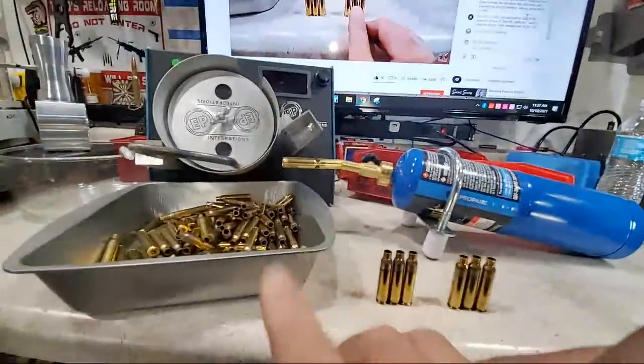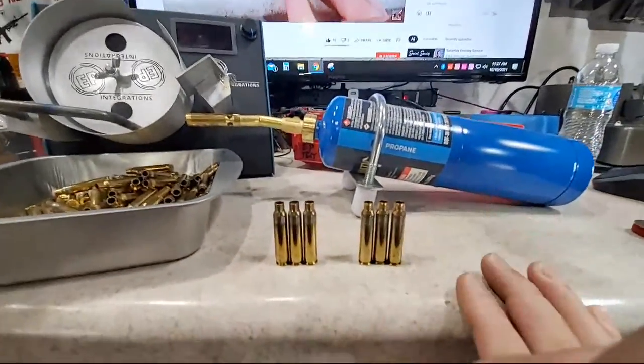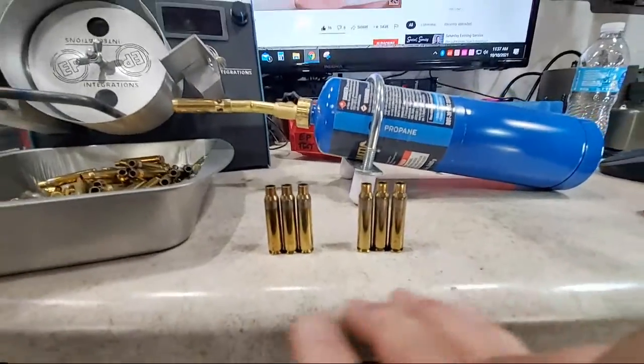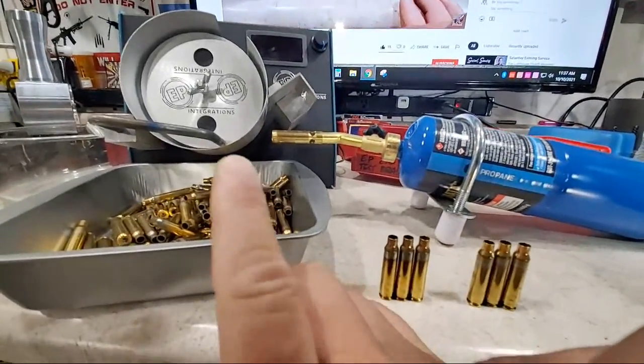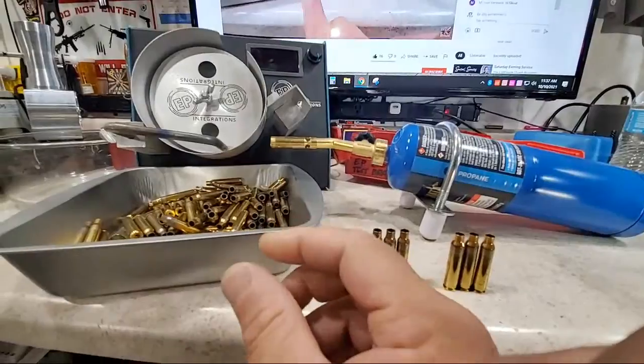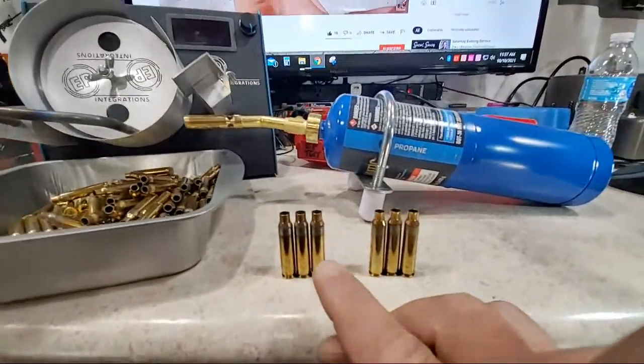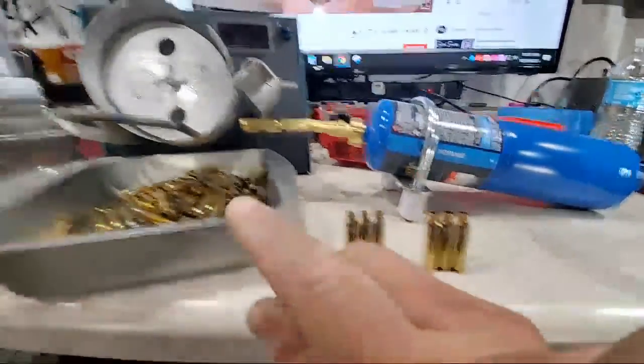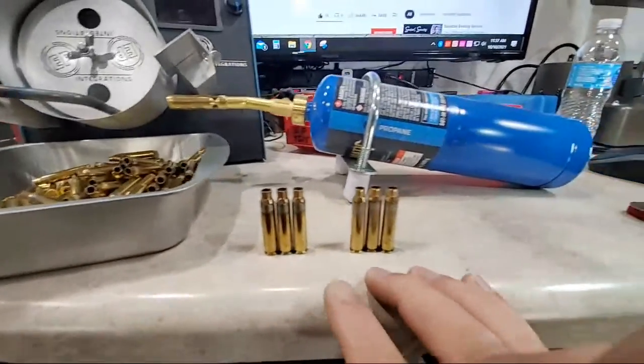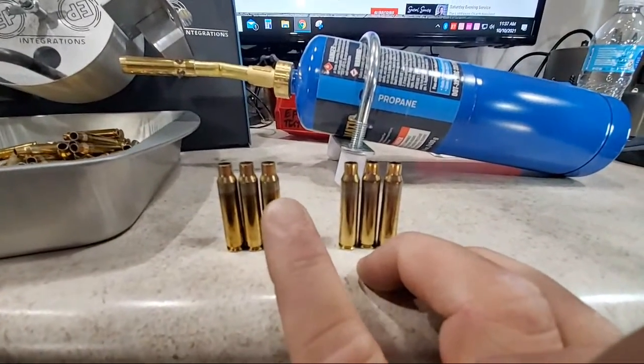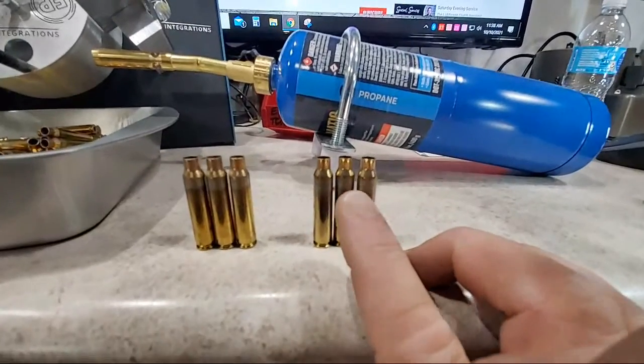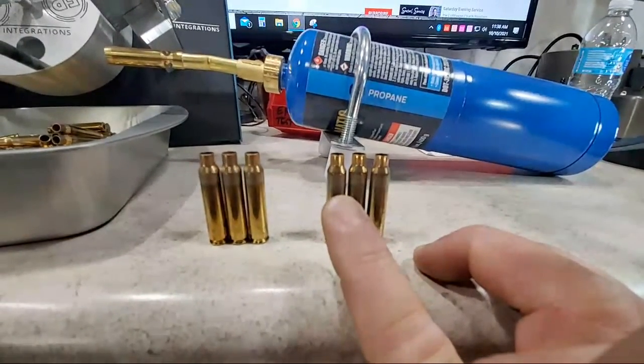And that's why I like using the glow method. Not saying those that use temp lacquers are wrong, but I look at the amount that that brass starts to glow. The second the neck and the start of the shoulder starts to glow, I get it out of the annealer. And that tells me that it has been annealed. And just because it doesn't show an anneal mark does not mean it's not annealed.